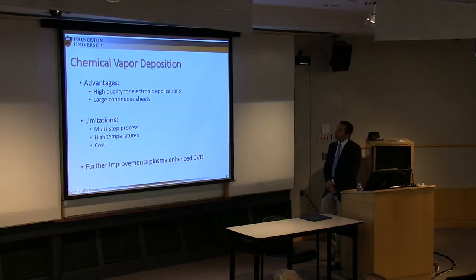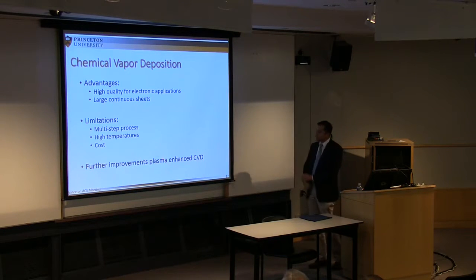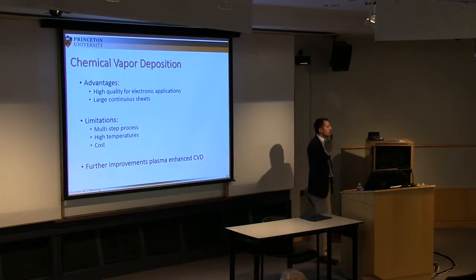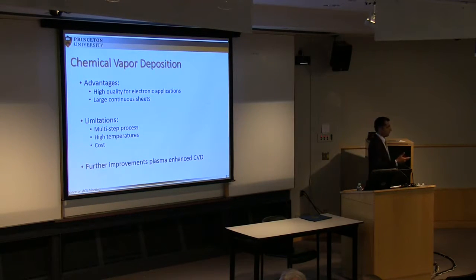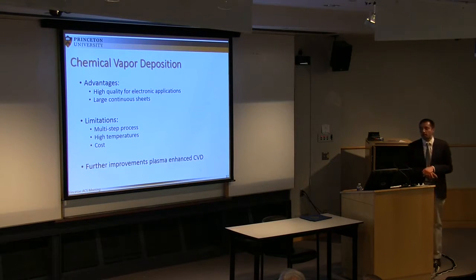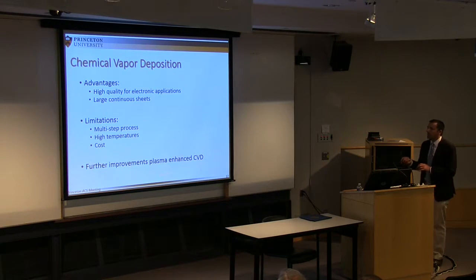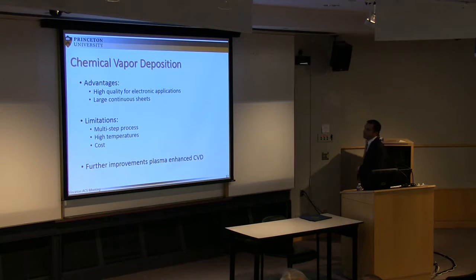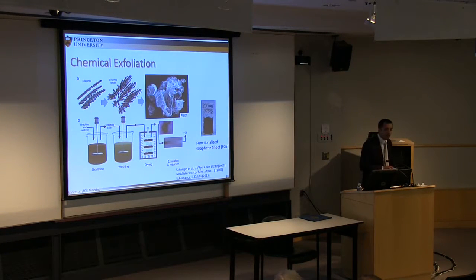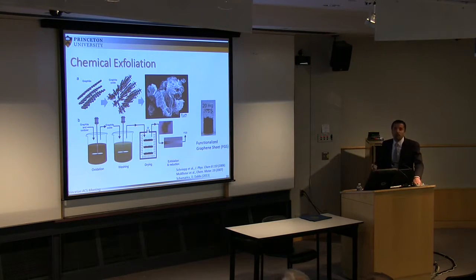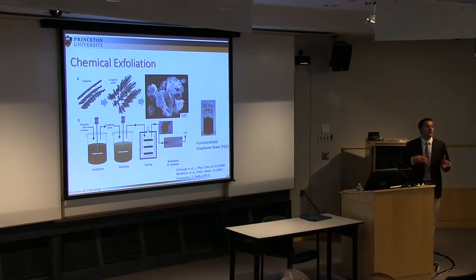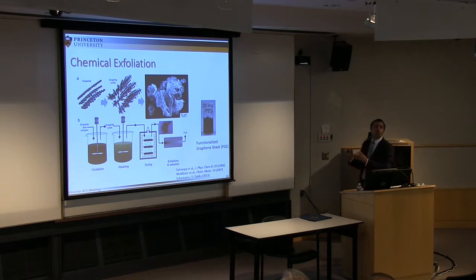However, despite that, very recently I found a group in Korea, again, they came up with a plasma-enhanced CVD. Again, plasma-enhanced CVD is not new. For the nanotubes, it has already been widely used. And doing that, they were able to synthesize pristine graphene at room temperature, which is very interesting. So now, I will talk about the other route, the chemical exfoliation of graphite to obtain functionalized graphene, so the defective graphene.